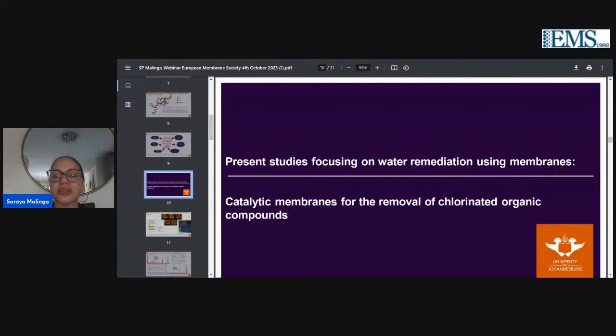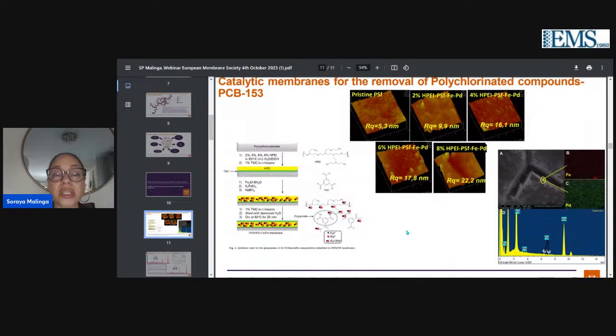So in the last slide, I will just focus on a grouping of the different types of membranes. I have not included all my work, but I've tried to group it in such a way that there is flow. We have prepared catalytic membranes for removal of chlorinated organic compounds. We used a thin film preparation method, where we embedded iron and palladium within the thin film, which was sandwiched between the bottom layer, which is green, and the top layer. Then the bimetallic coexisted, hopefully, inside that very thin film layer.